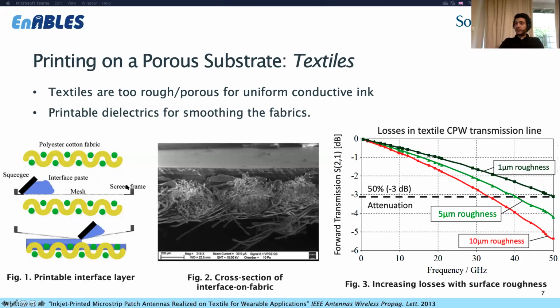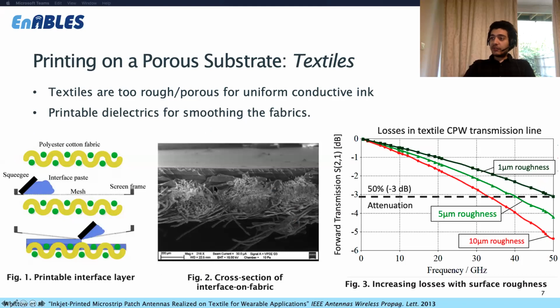So we have developed a method of using printable dielectrics to smooth the fabrics and smooth porous substrates and make them more printing friendly. So what we use is we have our fabric substrate, we get a screen printer, we have an open mesh, which doesn't have any geometry, which doesn't have any patterns, and we squeeze our interface, which is a dielectric material, and then we can actually tune those dielectric properties. And we have a smooth layer, which, as you can see in the SEM cross section, gives us a nice fabric, which has got less than 10 micrometer surface roughness, which allows us to print our conductive traces directly, reducing the cost and reducing the amount of inks that you need to print to fill the textile holes.